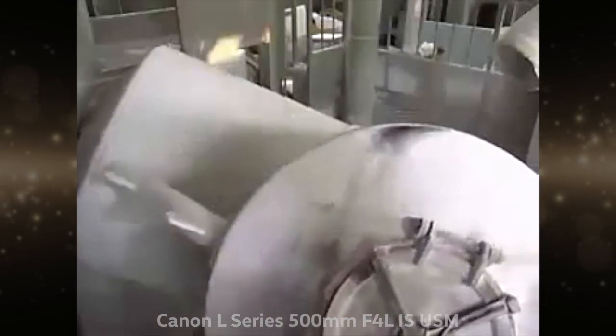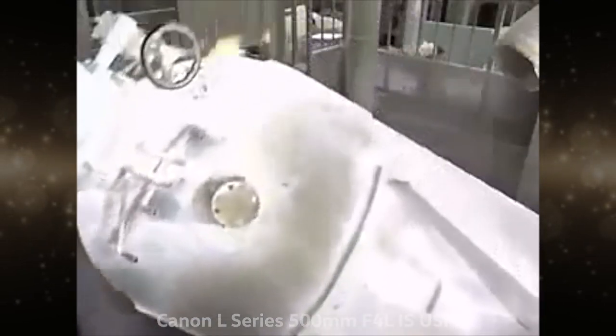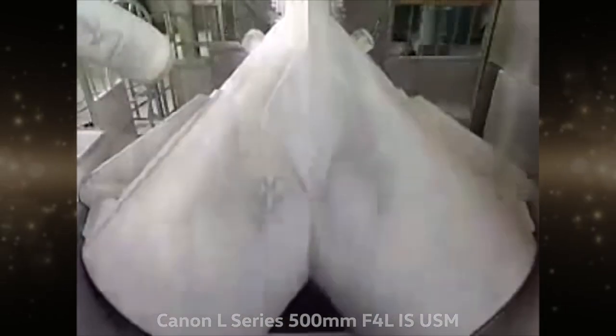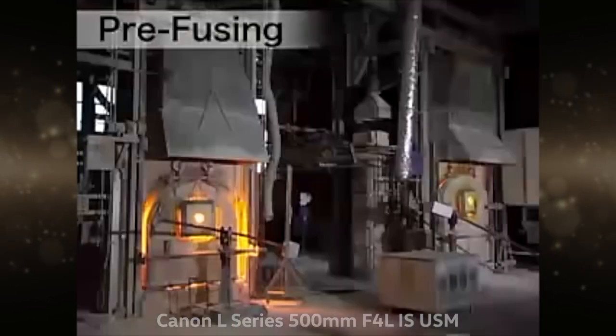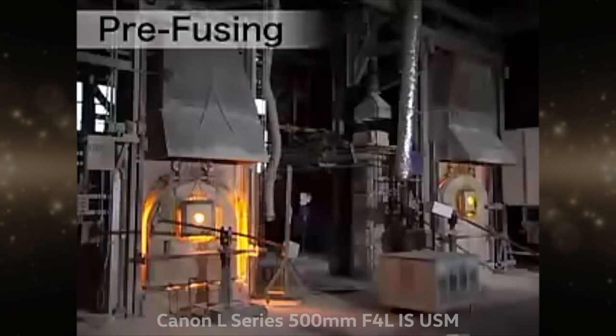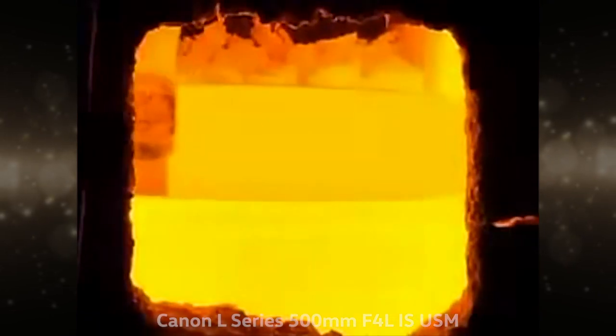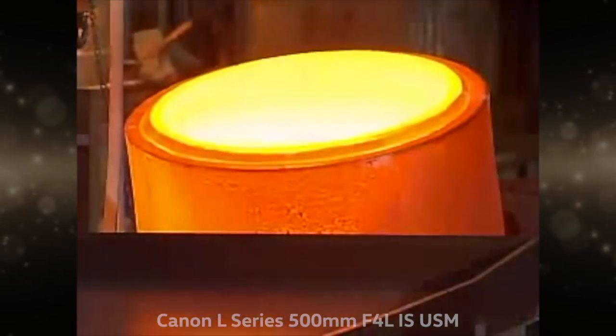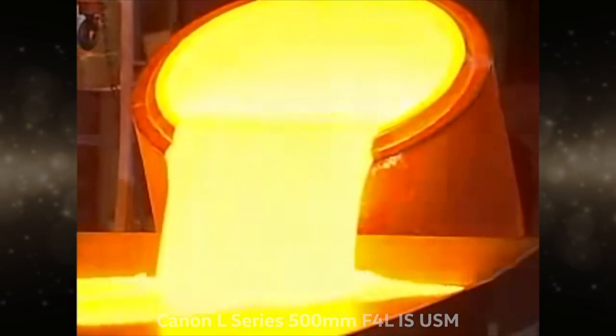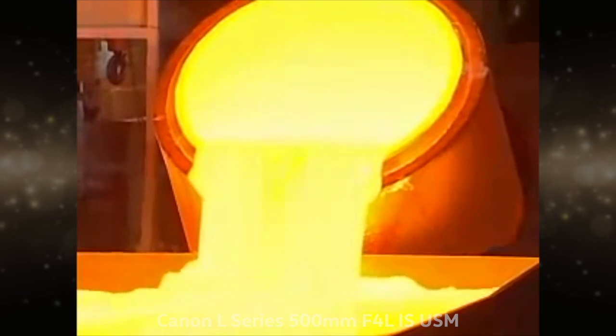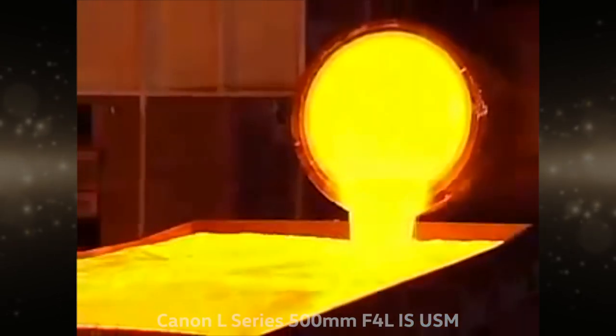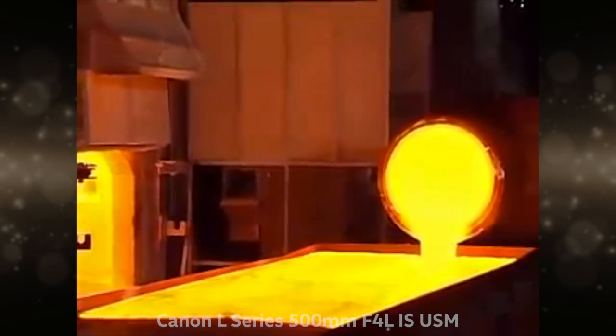Impurities such as iron that cause reduced transmittance are removed to the order of parts per million, and each material is precisely measured and placed into the V-shaped mixer. The blended primary raw materials are placed into a platinum or quartz crucible and fused in a furnace under strict temperature and time control. This is molten glass. The glass is poured into a pallet in its ultra-high temperature state and allowed to cool naturally.